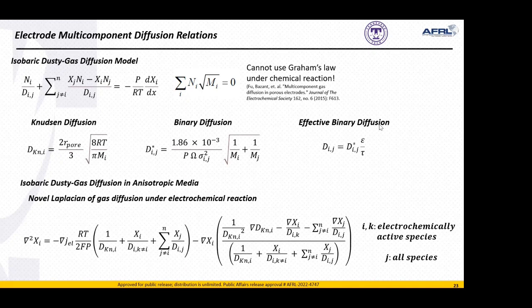Now, previous papers have used Graham's law, which just says that the cross diffusion of species is going to be related to the ratio between their molar fluxes and their molecular weights. And that would be true if we were just looking at a porous geometry. However, this is not true in the case of chemical reactions. We cannot use this equation anymore to simplify the dusty gas model.